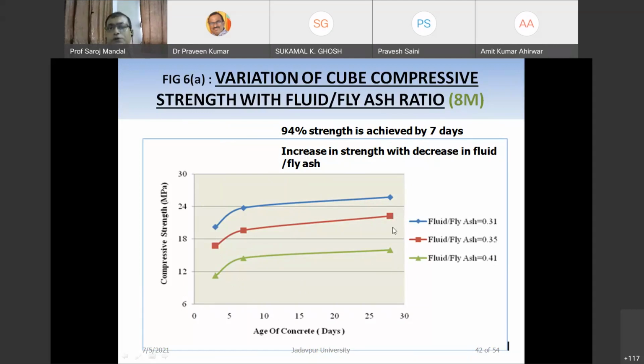Another important point is that at 7 days, we can get almost 94% strength. The increase in strength with a decrease in fluid to fly ash ratio is quite natural, as we are using more water in that system, where voids become more, so naturally the strength will be less. But one of the major important things is that we can get almost 94% strength by 7 days, right? That is the advantage of this. But the only thing is we have used heat activation here.